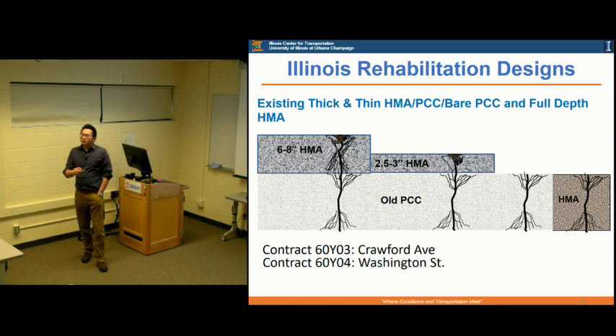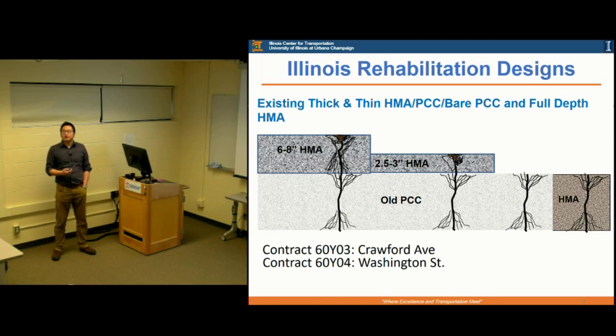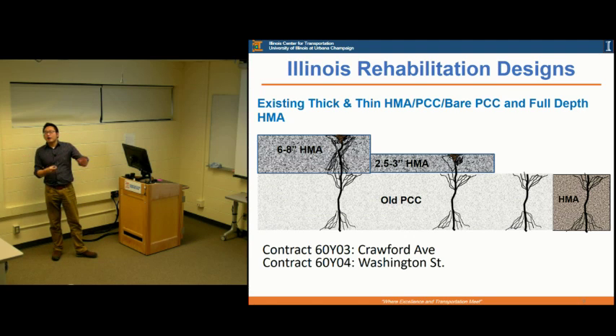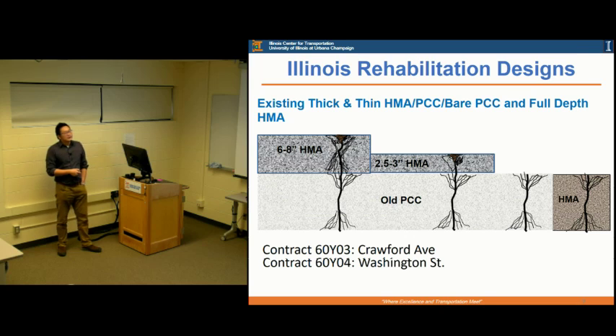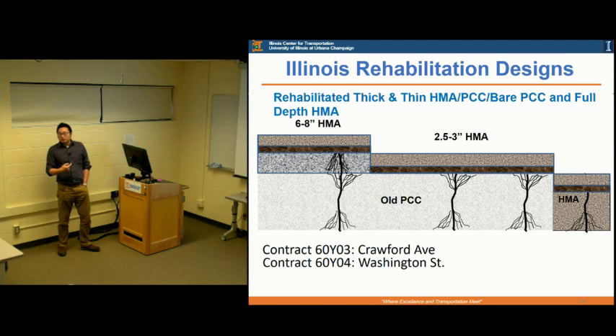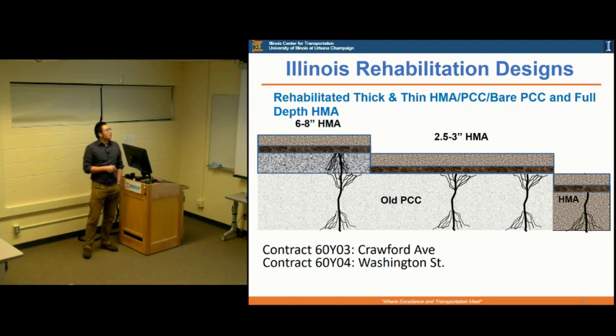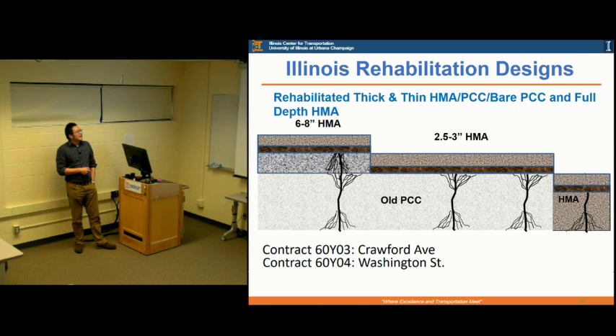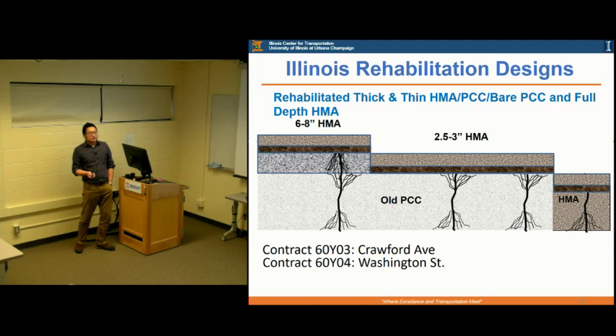In Illinois we have a lot of old roads, so we want to do a lot of rehabilitation design, because you cannot just remove everything. You're still going to build a new road on top of that existing pavement. You see there's a lot of distresses, a lot of cracking on the existing pavement. So what we're going to do for rehabilitation is put a very thin, less than 1 inch, level binder course, and then put an HMA overlay. For each different existing pavement, you can still use the same methodology: put a level binder and then the HMA. But still you're going to do some milling, trying to minimize those distresses in the existing pavement.